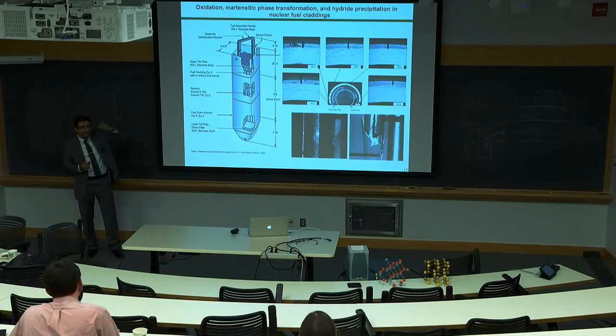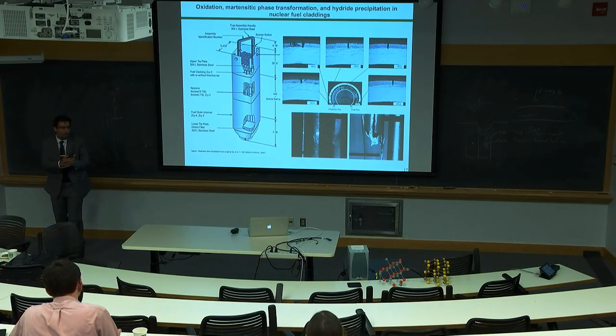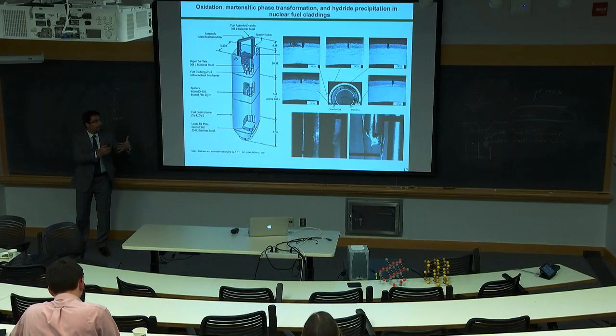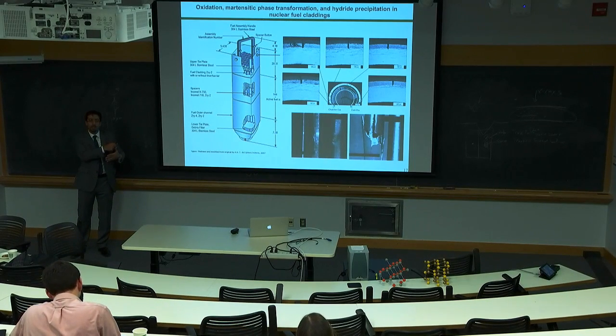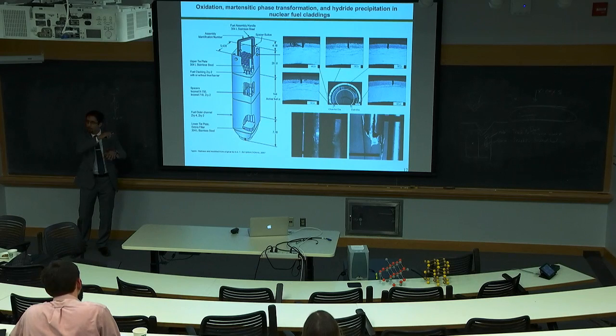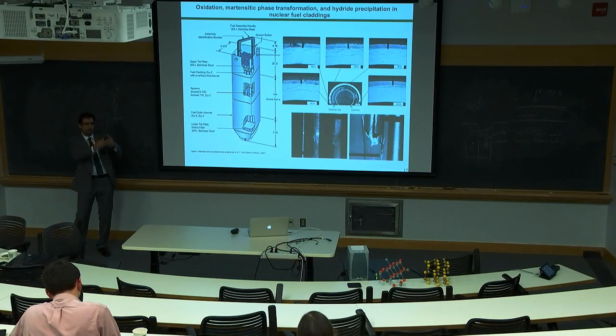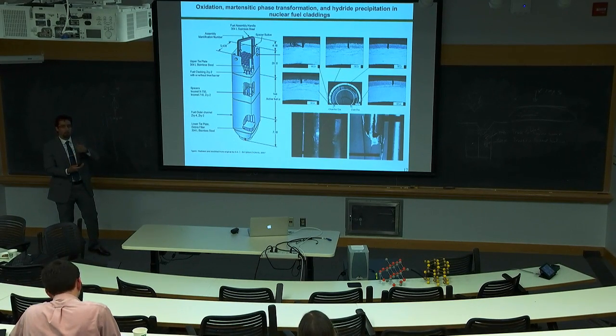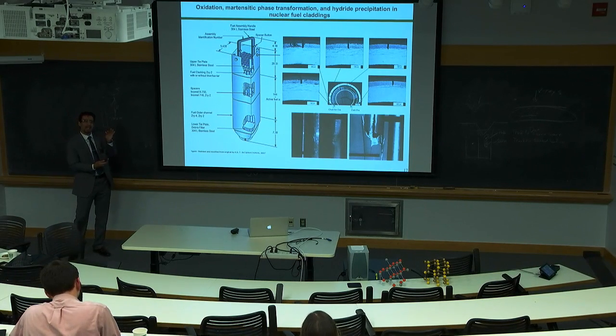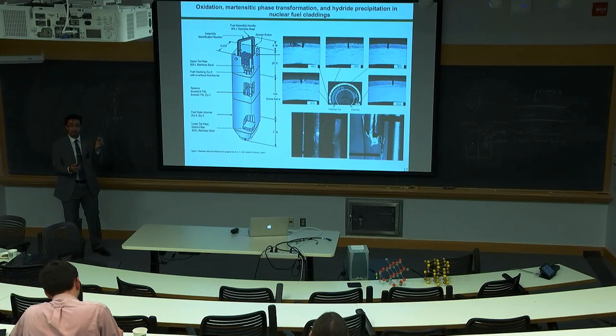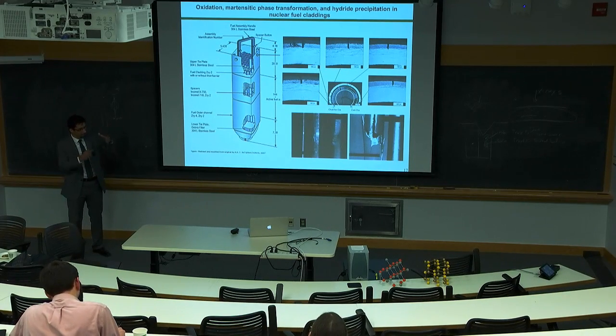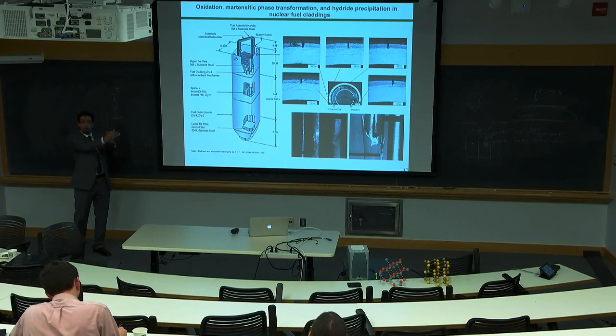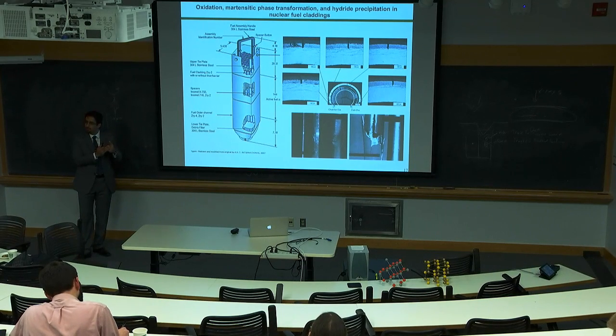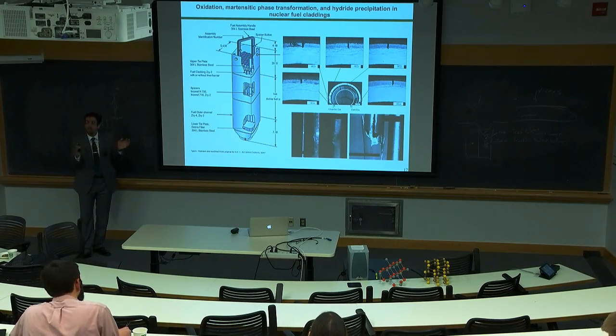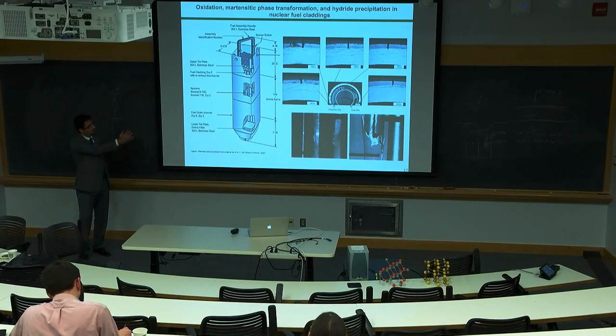The cladding is a zirconium alloy, usually called zircaloy. What is used as the coolant is water, high-pressure water at high temperature, so it will react with the zirconium. Initially, it will create a very thin oxide layer. It's a tetragonal phase, a pretty good phase actually. But as the oxide scale grows, it will transform to a monoclinic phase, which is not a good one. We get volume expansion, we get lots of cracks, and this is what happens.